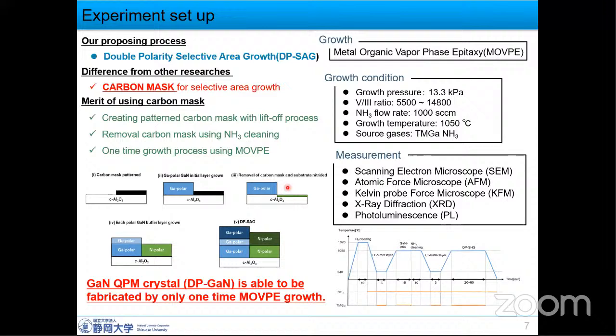The growth conditions are shown here. Growth pressure was 13.3 kilopascal. The V/III ratio was about 10,000. Ammonia flow rate was 1,000 sccm. Growth temperature was 1,050 degrees C. The gallium source was trimethylgallium, and the nitrogen source was ammonia. The evaluation methods used are SEM, AFM, KFM, XRD, and photoluminescence.